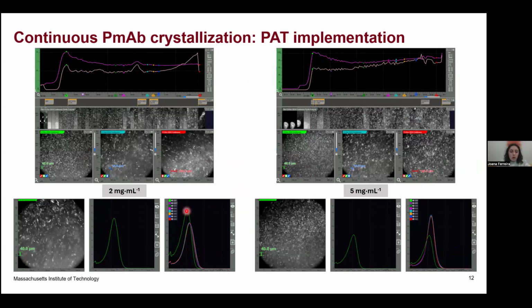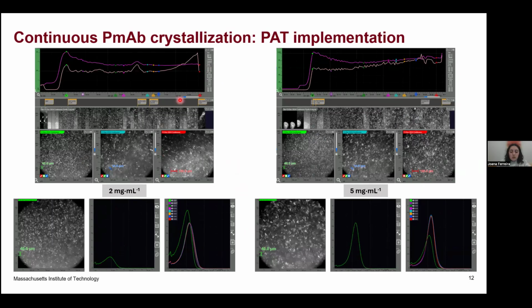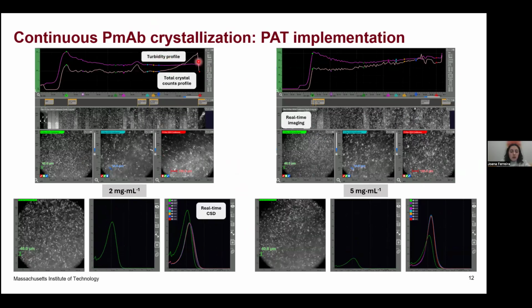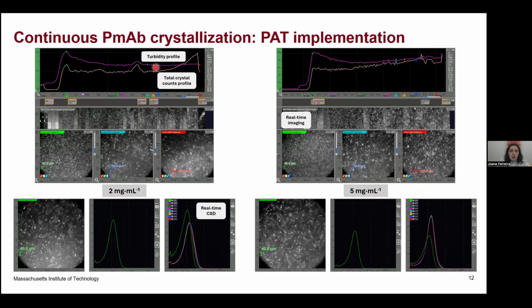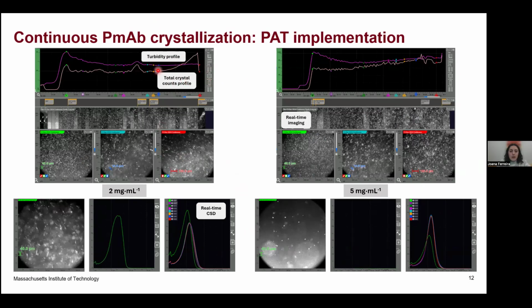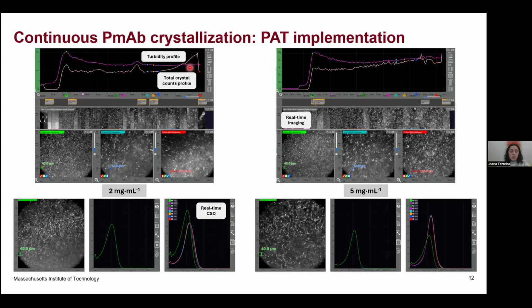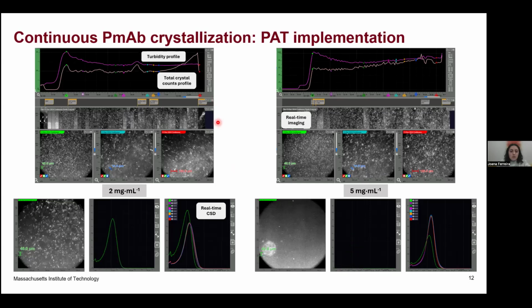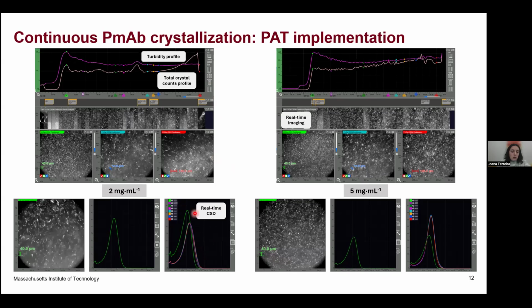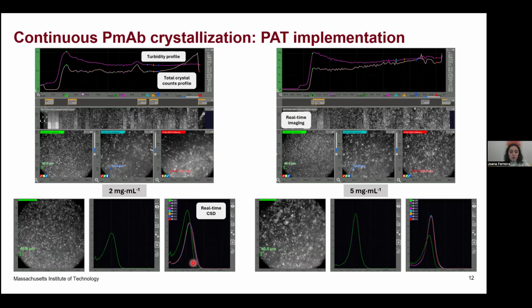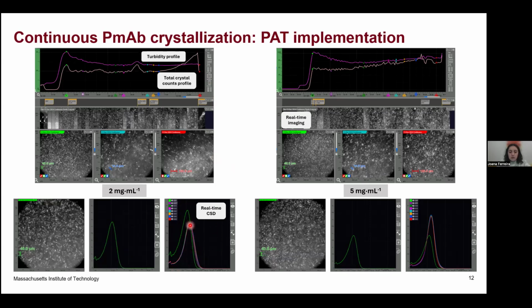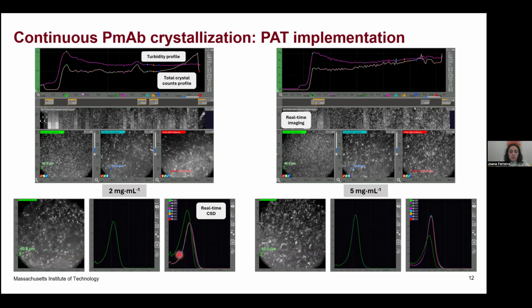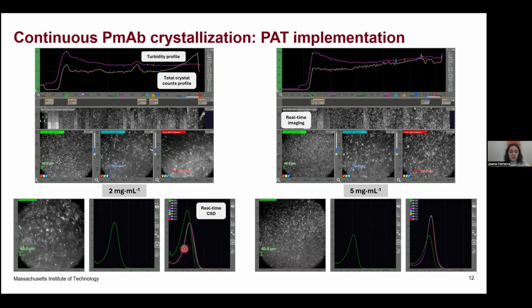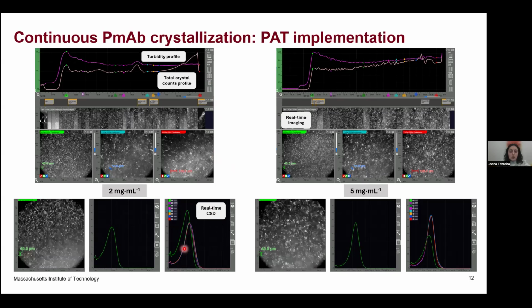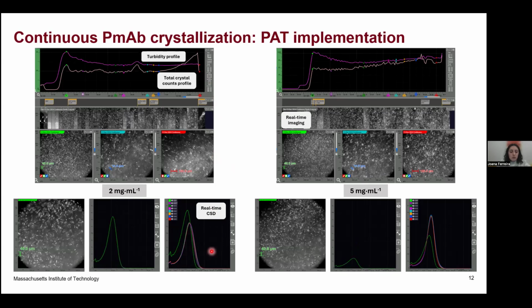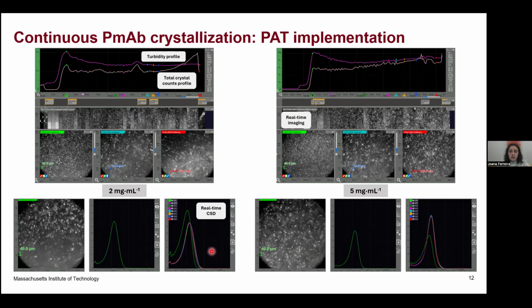tools. So what is interesting to see here, we can look at the turbidity and total crystal counts, and as soon as we reach a stable plateau, it means that we reach a steady state. So what does reaching a steady state mean? It means that you look at your real-time crystal size distributions, and the lines are overlapping because there is no further nucleation or growth taking place. You just reach a steady state.